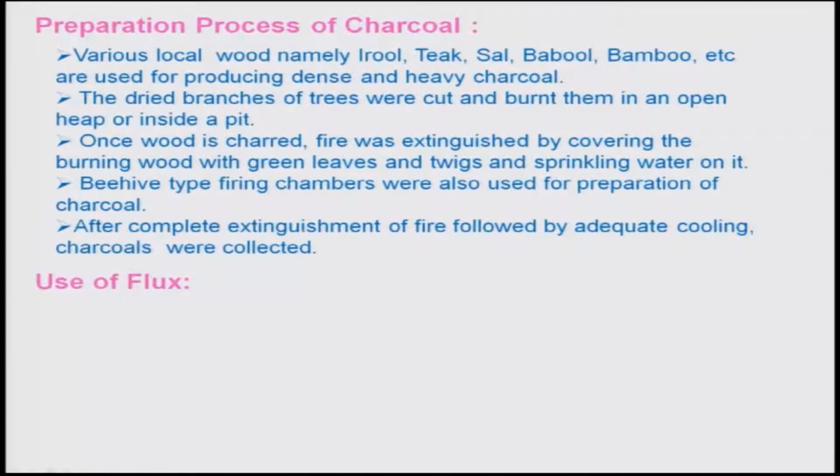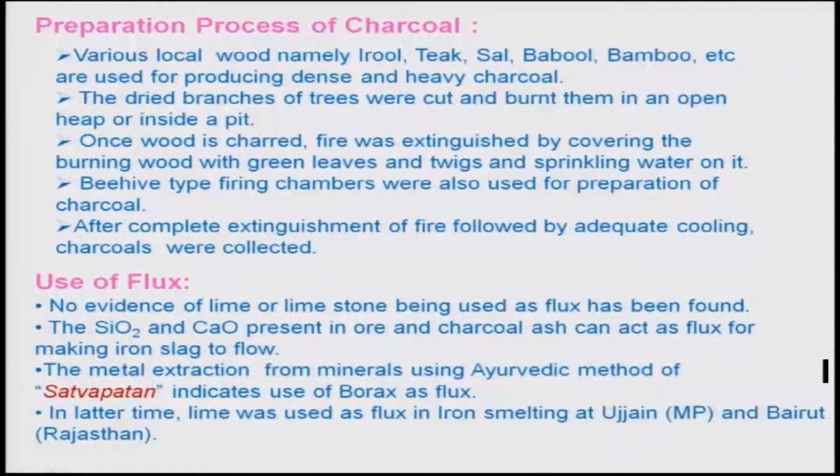And there is no evidence of lime or limestone being used as a flux, however, the silica SiO2 and CaO present in the ore and charcoal ash can act as a flux for making iron slag flow. The extraction from material used by the Ayurvedic method, that is Satvapatan, indicates use of borax as a flux.